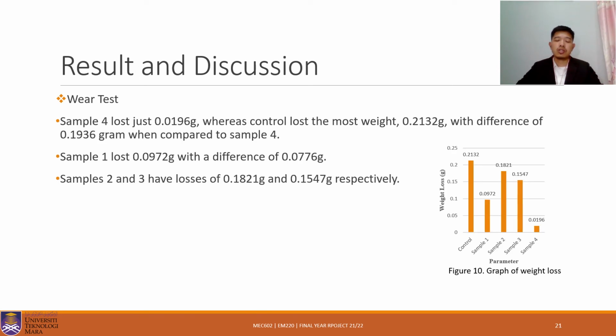Figure 10 shows sample 4 lost just 0.0196 gram, whereas control lost the most weight at 0.2132 gram, with a difference of 0.1936 gram when compared to sample 4. Sample 1 lost 0.0972 gram with a difference of 0.0776 gram. Sample 2 and 3 have losses of 0.1821 gram and 0.1547 gram respectively.